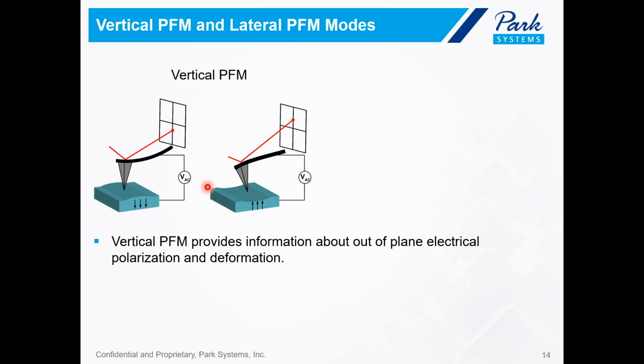So in PFM, there are several different modes. The first that I will describe is the vertical and also lateral PFM modes. The position sensitivity of the photodiode allows PFM to identify the direction of the electrical polarization in active piezoelectric and ferroelectric domains. So in this image shown on this slide, if there's no deflection of the cantilever, the laser spot would stay right here at the center of our photodiode, or the 0, 0 coordinate.